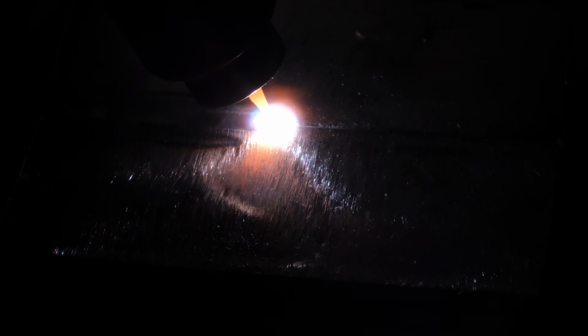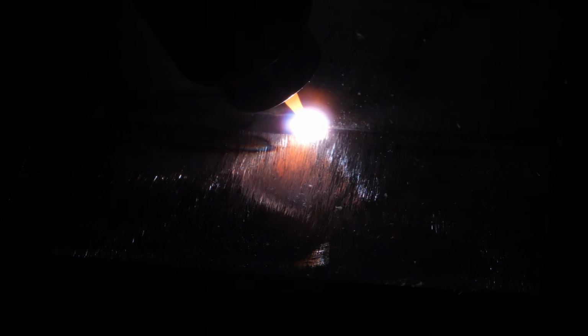Everything is fusing together nicely here. However, my travel speed is a bit on the high side, and you can tell that because of how narrow that fusion weld is. And that's something you got to be careful about. You can also tell by the heat affected zone coloring how narrow it is and close to the weld, that it was run a little bit too fast. Now let's just look at it without commenting.